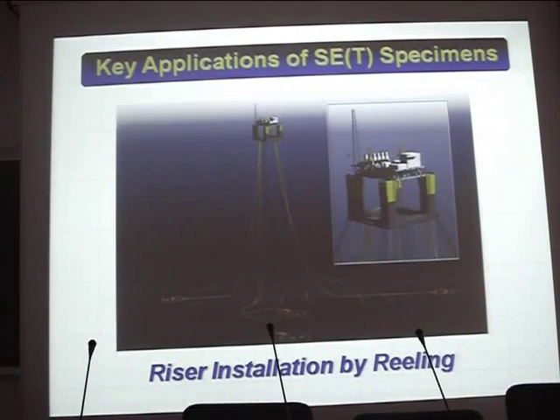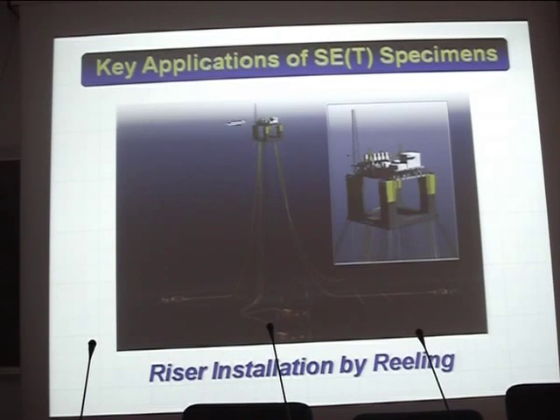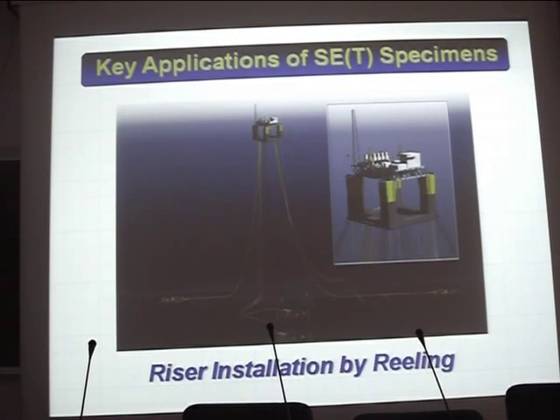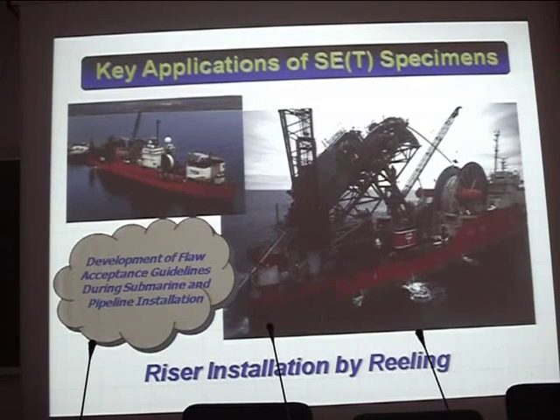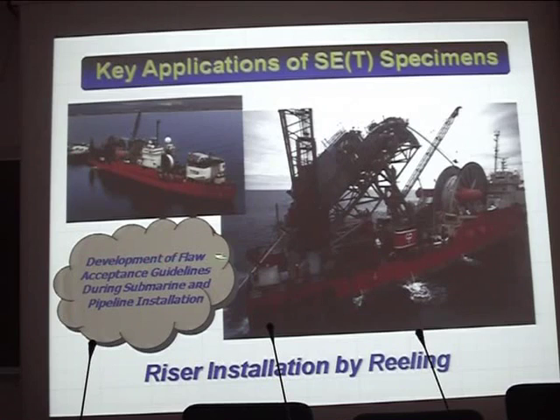One of the key applications for these SENT specimens is in riser installation by reeling. These are deep water floating production off-loading units. The idea is to optimize installation, so a lot of risers are laid down on a single FPSO. To speed up the installation, these risers are welded on shore, reeled on a very large drum — perhaps a 12-inch or 14-inch pipeline — and then deployed. The reeling process introduces large plastic strain on the girth weld. We need to develop guidelines for flaw acceptance during pipeline installation.